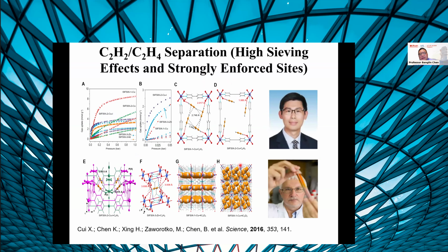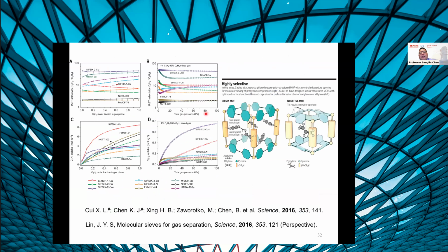And sometime in 2015, Huabing and Mike contacted me showing their result on this MOF material for ethylene separation. You will see that the mechanism is the same as we discovered in the carbon dioxide material. So you will see a suitable pore size exactly captures 4 acetylene molecules, and the terminal fluoride has a specific site for a little bit stronger recognition of the acetylene molecule. So this resolves the trade-off, having a high uptake and high selectivity.